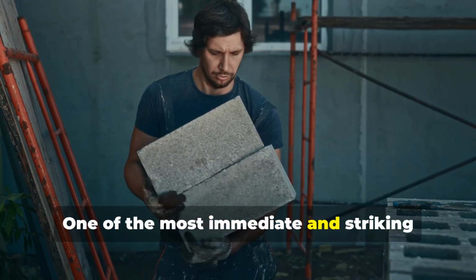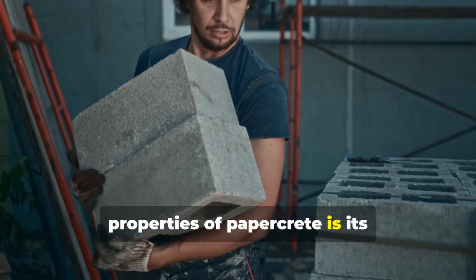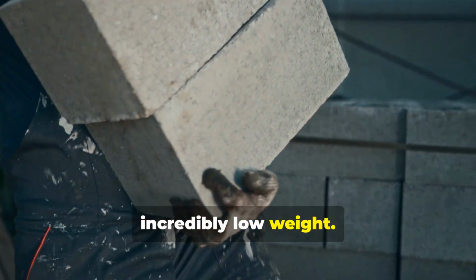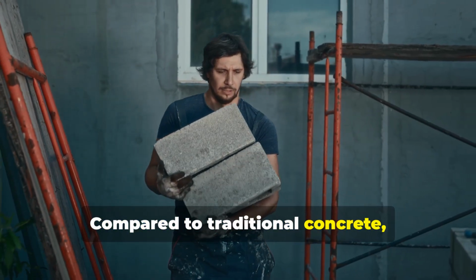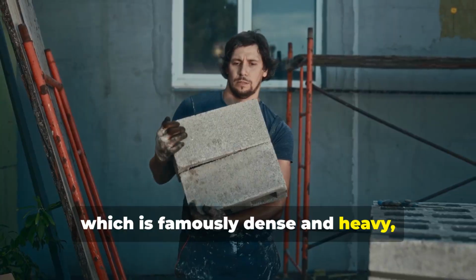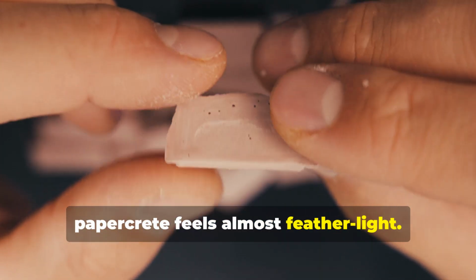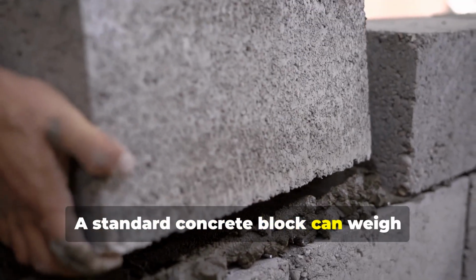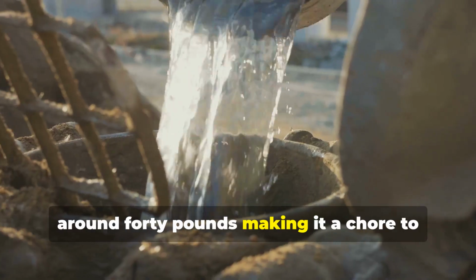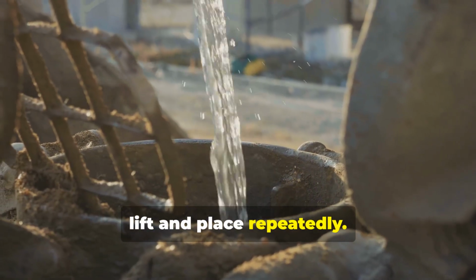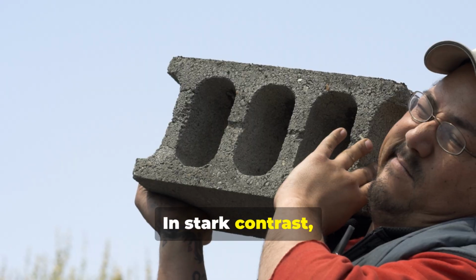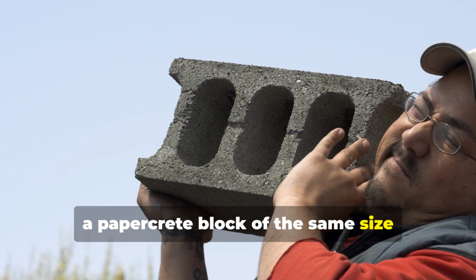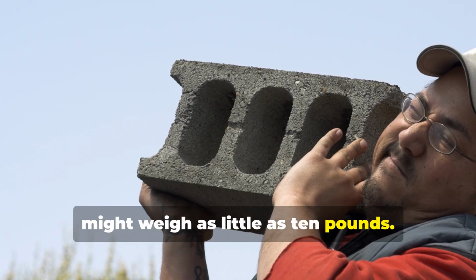One of the most immediate and striking properties of papercrete is its incredibly low weight. Compared to traditional concrete, which is famously dense and heavy, papercrete feels almost feather-light. A standard concrete block can weigh around 40 pounds, making it a chore to lift and place repeatedly. In stark contrast, a papercrete block of the same size might weigh as little as 10 pounds.